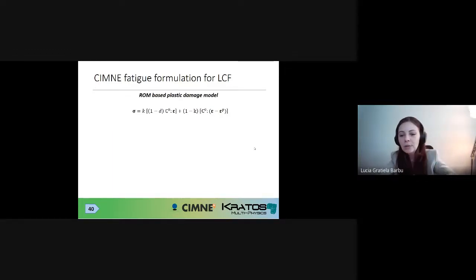I have to say this is a model that I'm deeply in love with, because the rule of mixture is something that has been used in the composite world since the 1960s. It's a very old idea, but it has never been used for describing the behavior of a homogeneous material. Because what we are doing here is we are assuming that in a specific volume of a homogeneous material, we have a volumetric part which will behave according to plasticity laws, and we have the remaining, the complementary volume part, which will behave according to damage.